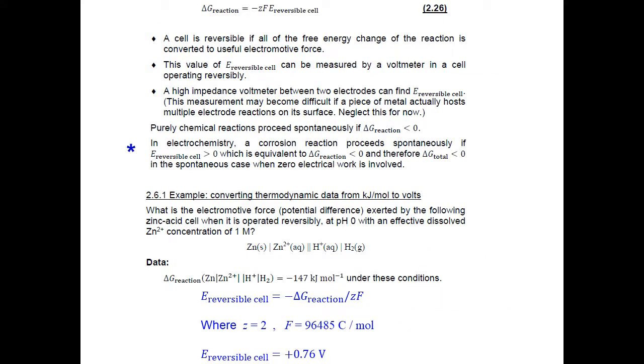What does it mean physically? Well, a cell is reversible, essentially, if all the Gibbs energy change of the reaction is converted into useful electromotive force. And this value of E can be measured in practice. If you have your cell like shown in diagram 2.3.1, you could simply place a voltmeter between the two electrodes, and no resistor. There would be a negligible current flowing through a high impedance voltmeter, and it would simply measure the reversible cell potential.